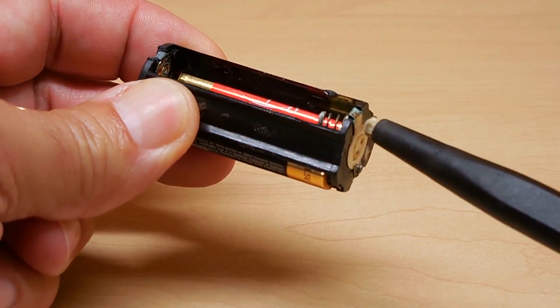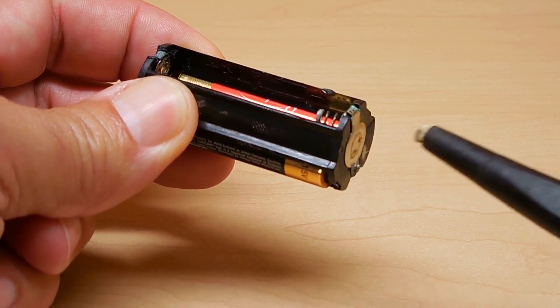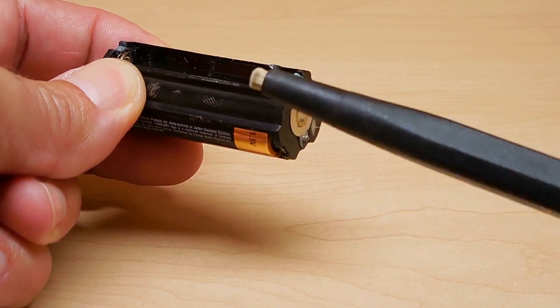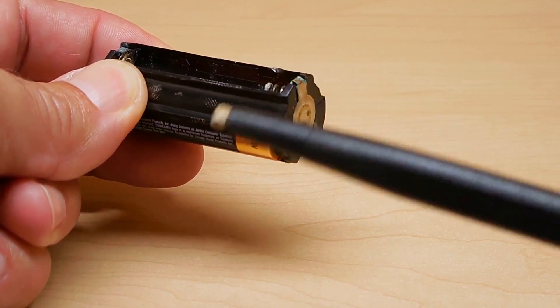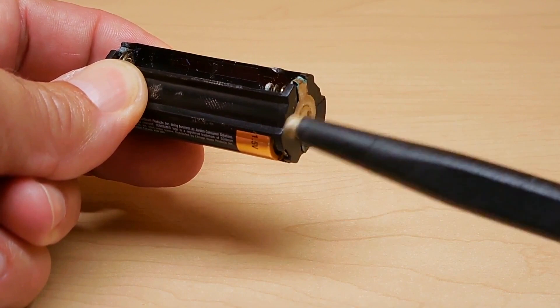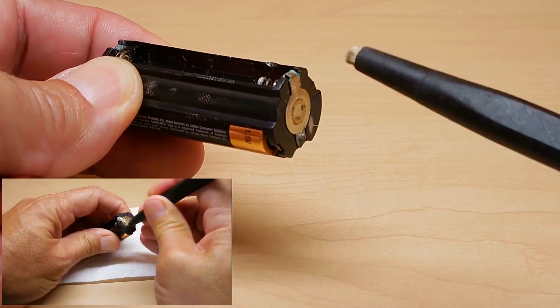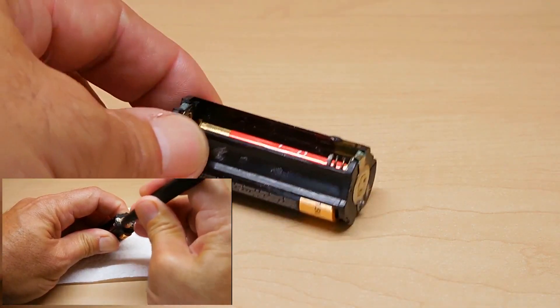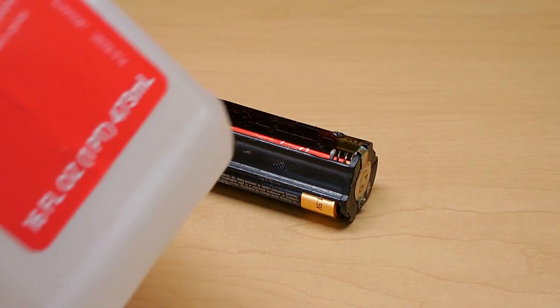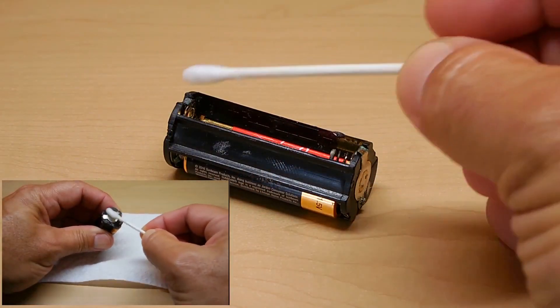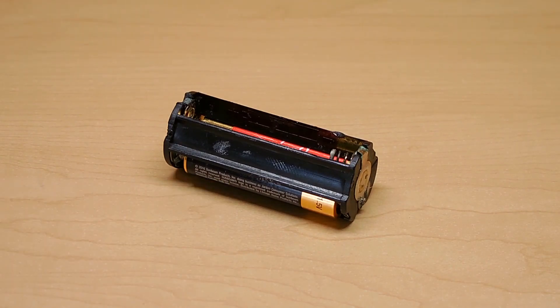If your holder has a wire leading into it that broke off due to the corrosion, you would simply clean that area using a tool like you see here. This is called a nic sander. You use it on the finish of your car. It cleans up the area where the paint chipped, so you can apply the touch of paint. Nothing more than fiberglass bristles. You would clean that area. Once you clean it, you would take some 91% alcohol, apply it to a Q-tip, wipe over all the areas that you cleaned, and allow it to air dry. Once the alcohol has fully evaporated from the holder, you can then mix up the epoxy as shown right here.